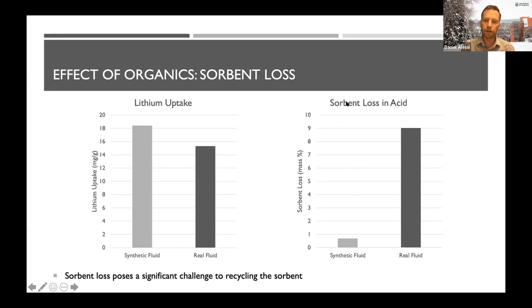But what is dramatic is the loss of sorbent. In other words, percent mass loss of the DLE material. In the synthetic fluid, we're looking at less than a percent. And in this particular brine, it varies very much depending on the brine you're testing. But in this particular brine, we were losing 9% of the sorbent mass in the first cycle. So what that means is the sorbent's basically gone after 10 cycles. Again, keeping in your mind that we're trying to aim for 100 cycles at least. Major problem in applying this technology to petroleum brines, right? Especially ones that have organics in them like this. So it's an issue that we needed to solve.